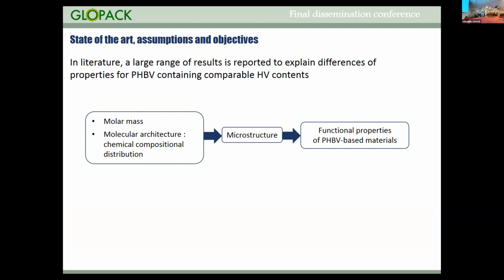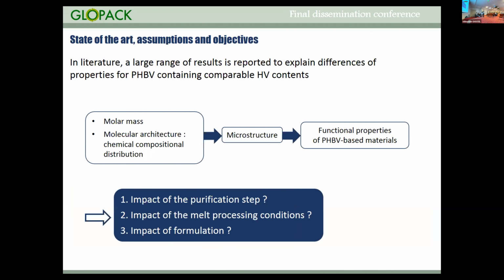In the literature, a large range of results is reported to explain differences of properties for PHBV containing the same HV contents. It could be the molar mass, but also the molecular architecture of the polymer. And what we wondered in the project, so additional questions, was first the impact of the purification step, how we can explain such unexpected behavior. The second question was the impact of the melt processing conditions. And the third question, how we can play on the formulation also to change and to modulate this behavior.